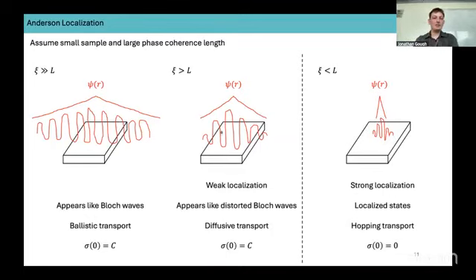Now, as we increase the disorder even further, we enter this strongly localized regime. Here, the wave function is much smaller than the sample, so it can be purely described by this exponential envelope or a localized state. So here, transport is by another mechanism called hopping.